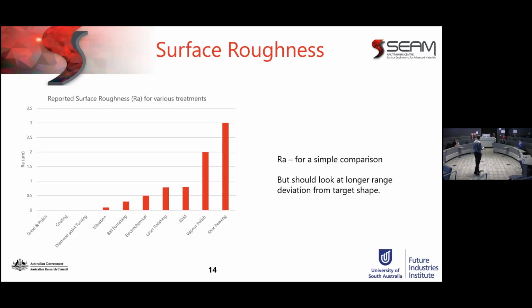You choose a surface finishing that's fit for purpose. So if you're doing a hydraulic rod, trying to get rid of hexavalent chrome and putting down the laser plating and then doing super finishing, that might be enough. You don't want to add cost that you don't need to. But if you're making an optical surface that you want to mirror coat, then you're going to need to go down to the diamond point turning or coating.